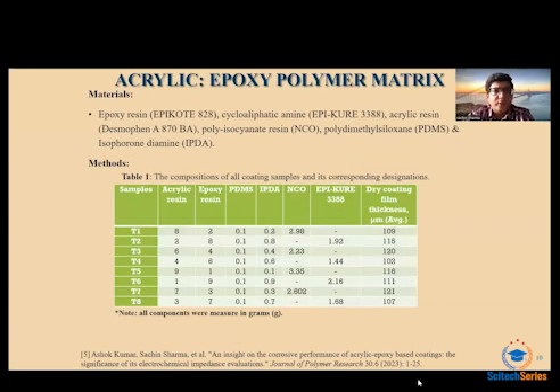So these are the materials that were used for this study. We used the epoxy resin, EPIKOTE 828. We used the curing agent, EPI-KURE 3388, and then acrylic resin 870BA, and its curing agent NCO, which is also known as polyisocyanate resin. And we also used polydimethyl siloxane, PDMS, and isophorone diamine, IPDA, mainly to ensure that the cross-linking had occurred between both the resins. So the samples were fabricated as illustrated in table 1.